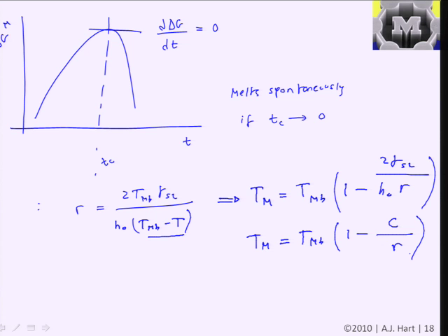So there's a limitation to this. It's not true that everything that's really, really small is a liquid at room temperature if you imagine an infinitely small R, but it gives us some kind of qualitative insight that the melting point of this small solid is lower as the particle gets smaller, and therefore there's more surface relative to the volume, and therefore it's more likely to melt.